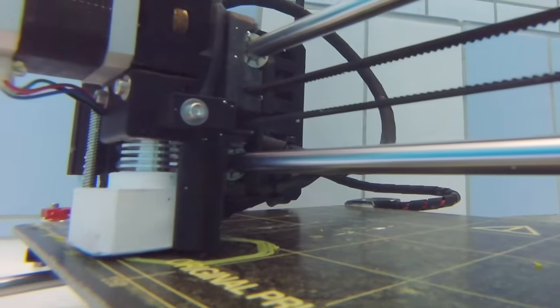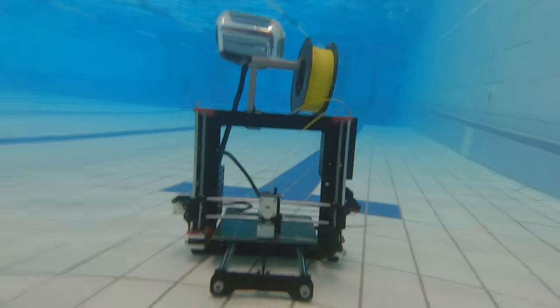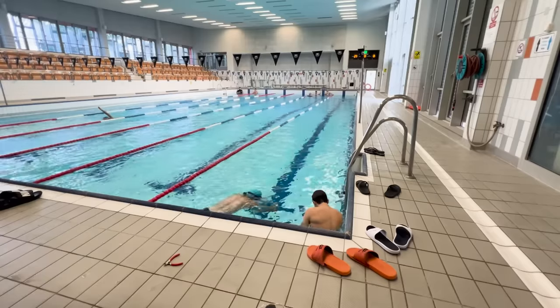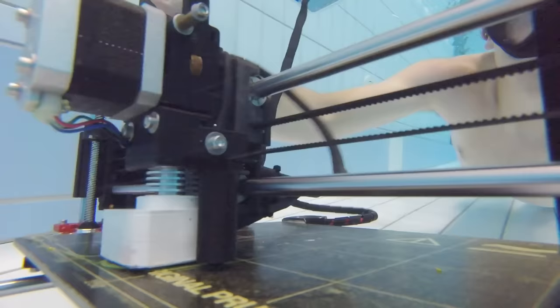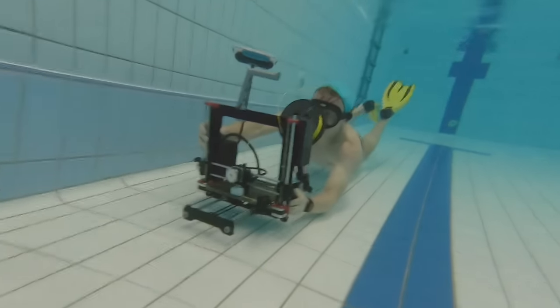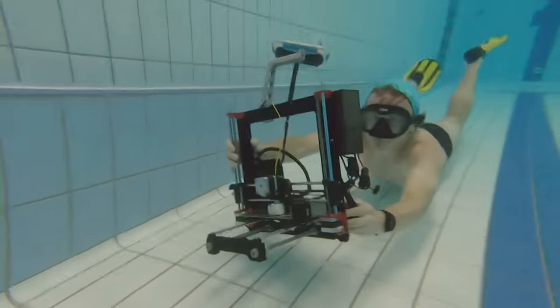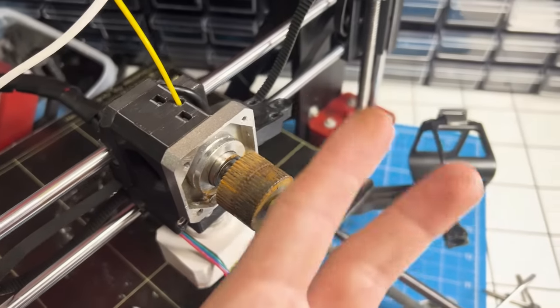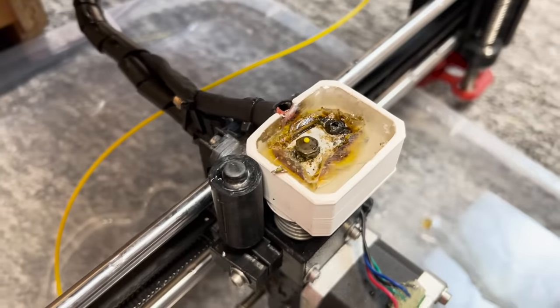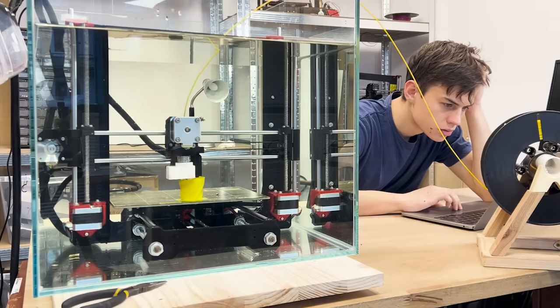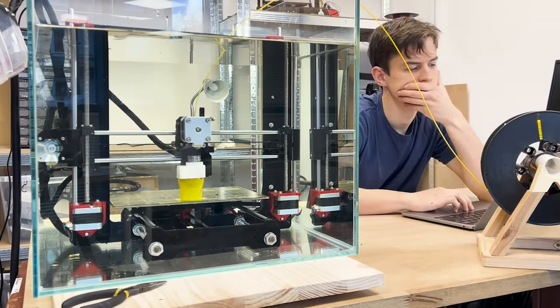Now let's see what we can do in the pool. We saw that the first layer stuck to the heat bed quite well on the first try but for some reason the spool kept falling off. We constantly kept fixing it until we realized that it's the water jet coming from this wall. When it comes to the prints... yeah it didn't work. Turns out after a week of constant printing it just slowly stops working. Specifically for two reasons. First reason is that by this point the motors corroded so much that they started to randomly jam and the second reason is that our epoxy heat block deteriorated a lot by this point.